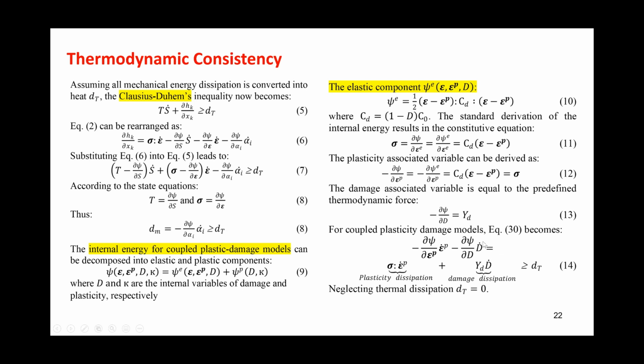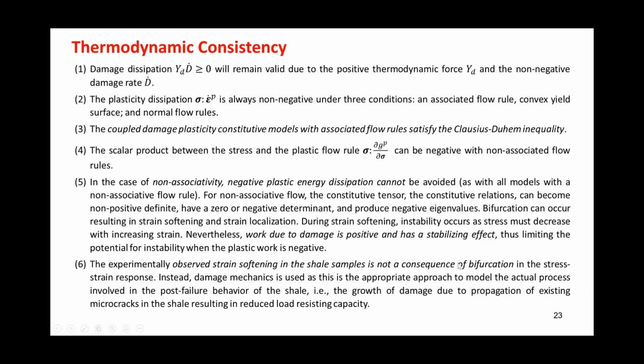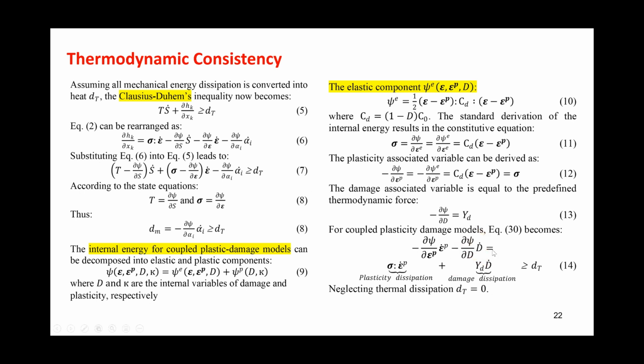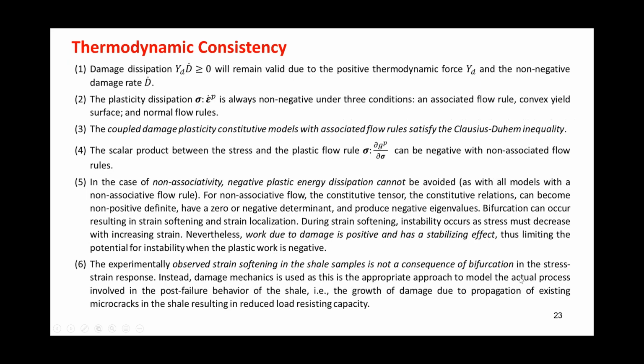Okay, so at the end of the day, we derive this equation. So the rate of work of the material, the change in strain energy due to plastic deformation, and the change in strain energy due to the change in damage should be equal to the thermal dissipation. So this is the work done by the material due to plastic deformation. I'm sorry, and this is the work done by the material due to the change of damage. So we have two: plasticity dissipation and damage dissipation. And since the sample is very small and it is very difficult to detect thermal changes, we can just assume that the temperature change is equal to 0. Okay, all right. These are the important things to note about the thermodynamic consistency of the material.